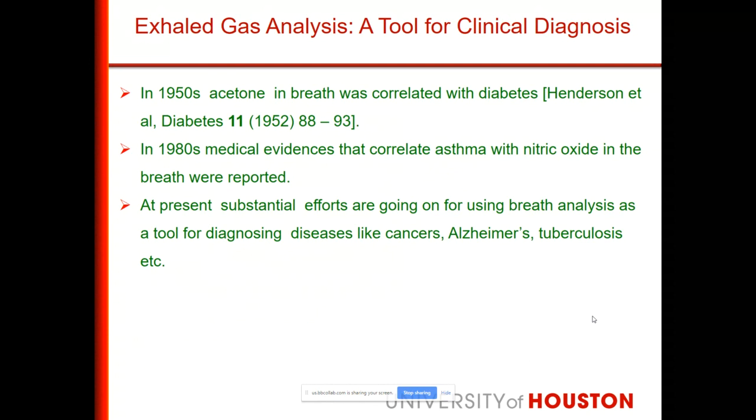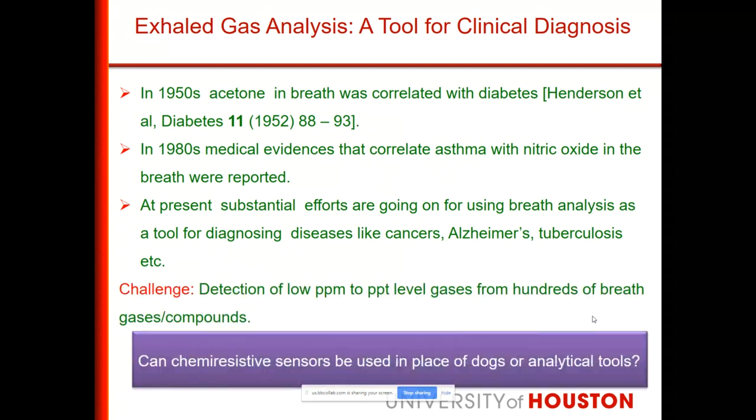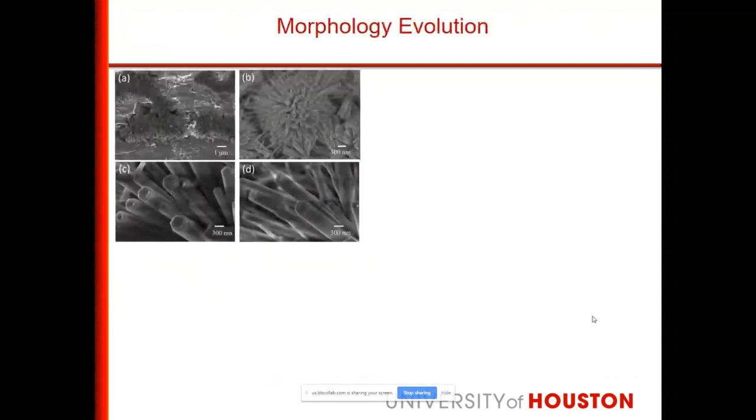So we developed the zinc oxide nanotube for that application. You can see this is an anodic oxidation process. Initially, these wires are formed, but after some time, these wires are drilled. You can see the small indents on the top, and the holes are drilled through the nanotube, not manually, but by an electrochemical process, electrochemical anodization.